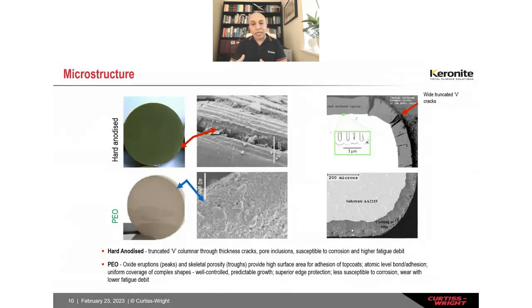Microstructure is quite key. On the top is the hard anodized coating, and the bottom is your PEO ceramic coating on the same alloy. You can see the corners in particular, this hard anodized coating often suffers from what we call truncated V cracks that result in massive fatigue drop, up to 50% fatigue drop. This is the cross section. You can see those truncated V cracks extend down to the substrate, of course, making it vulnerable to corrosion, fatigue drop, etc. The bottom picture here is the same region with the PEO. You don't see those wide opening defects or cracks. It's very uniformly covered as well. And you see the cross sections here, very uniform coverage.